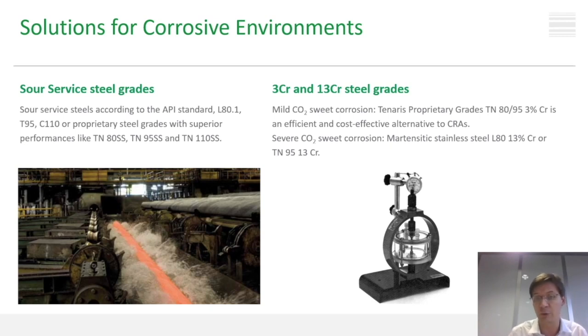One more typical condition for geothermal environment is sweet corrosion. CO2 is often present in geothermal brine, and CO2 may generate sweet corrosion, which will then translate into weight loss and eventually, at a certain point of the life of a well, into the loss of the well itself. In order to minimize that, again looking to a cost-effective solution, Tenaris is providing several options, which may go from the 3 chromium steel to 13 chromium. Obviously, the selection needs to be done based on the specific environment, of the specific field condition, in particular taking into account CO2 content, temperature, pressure. Nevertheless, the options provide a higher resistance to sweet corrosion, granting the suitability of the material even if it is exposed to a specific amount of CO2.